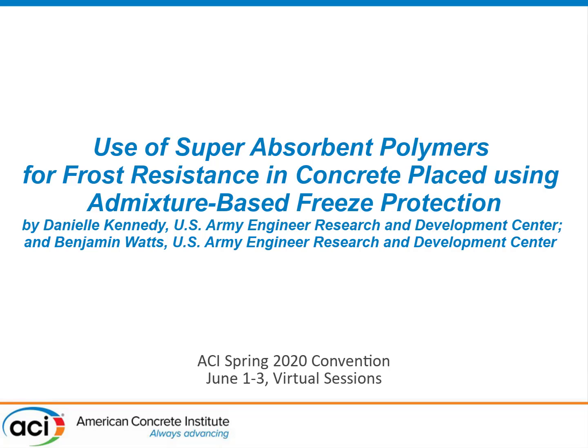It really depends. At CRREL, we do a lot of research on when you are in areas where you don't have a lot of access to typical materials and you are in the freezing cold. We did some research back in January up in Goose Bay, Canada, where it got down to 0 degrees Fahrenheit. And so it really depends.